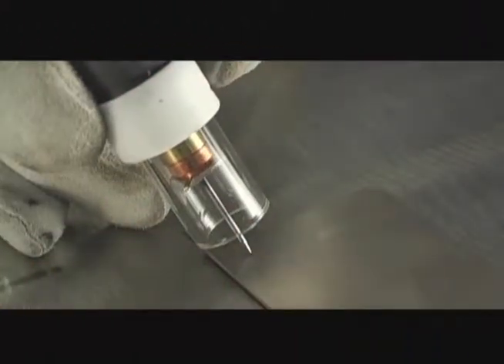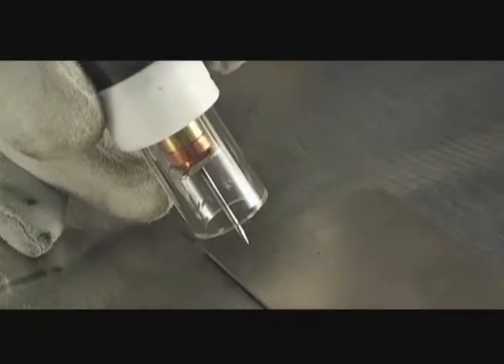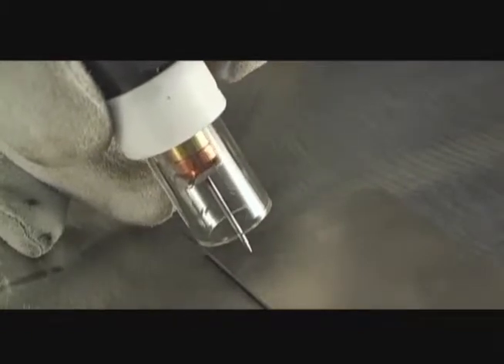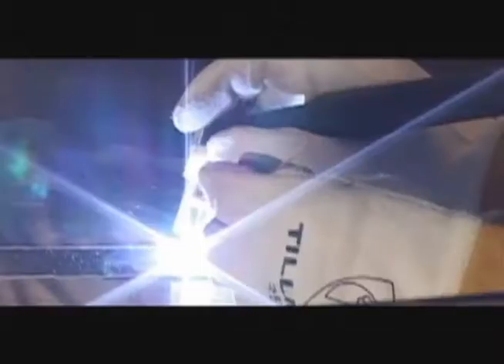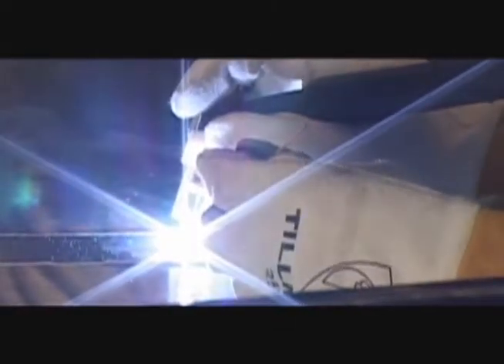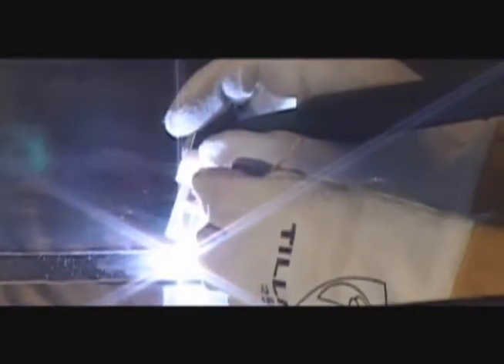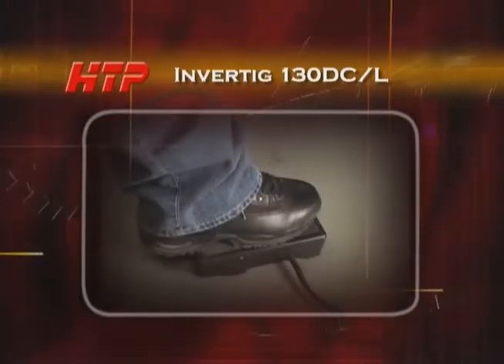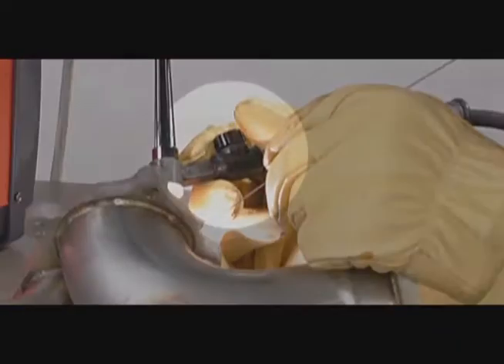We start the arc by the touch start method, which is easier than scratch starting and less likely to cause tungsten contamination. You touch the tungsten to the work, the machine senses contact and starts the arc when you lift the tungsten off the work. One of the nice features of the 130 DCL is the ability to remotely control the amperage by a foot pedal. This is an especially important feature for the novice welder as it gives you more control of the weld puddle and makes your welding much easier. Gas flow is controlled by a valve on the torch.